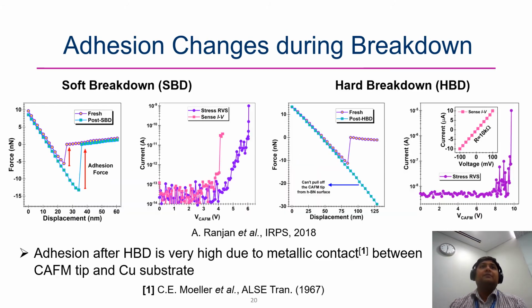What I'm showing here is that we were trying to measure both soft breakdown and hard breakdown. We first measure the adhesion between the tip and the hBN surface, then we apply some electrical bias, and this bias causes dielectric breakdown. Depending on the current compliance that we choose, it can be soft breakdown or hard breakdown. And after that, we again measure the adhesion.